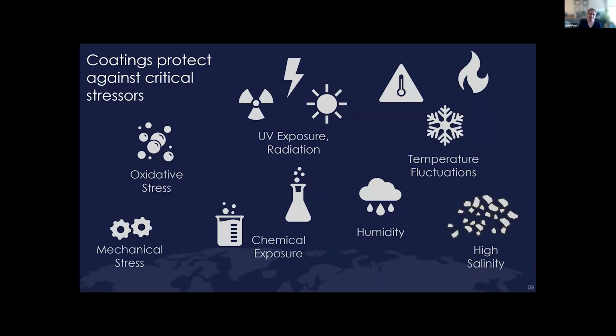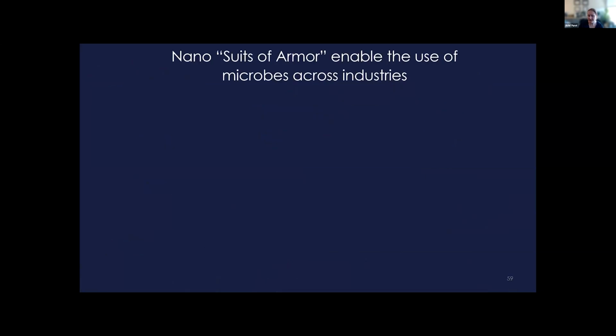And so then I tasked my students with thinking about every stressor they could think of in the lab to expose microbes to. What they came up with is oxidative stress, including UV irradiation, as well as the addition of things like hydrogen peroxide to our cell culture. Mechanical stress, which is often associated with spray drying or freeze drying processes, chemical exposure, radiation exposure, temperature fluctuations, both hot and cold, high humidity, as well as high salinity. And what we find is that across all applications we are interested in, these coatings protect each microbial strain from